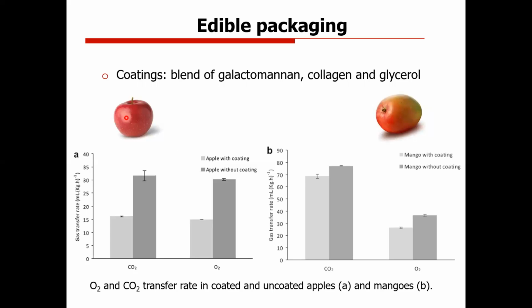I will show you some examples that we developed. In this case, it is a coating that was based on galactomannan, polysaccharide, protein, and glycerol. We applied these coatings to apples and mangoes, and then we checked if this coating was able to decrease the gas transfer rate of these two fruits. We found that for apple and mango, we are able to reduce the carbon dioxide and oxygen transfer rate for both products. So by applying a coating on the surface of these fruits, we are able to decrease the gas transfer rate. We also checked then, not with these products, but with others, the ethylene. So we are able to increase the shelf life by reducing the respiration process of the fruits.